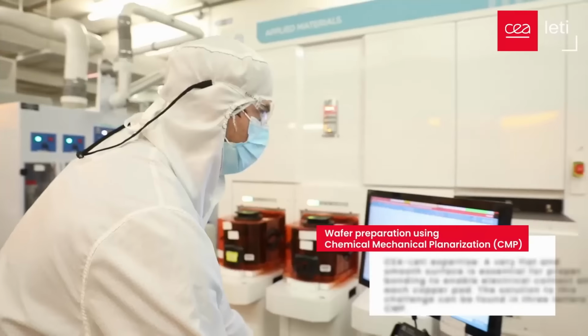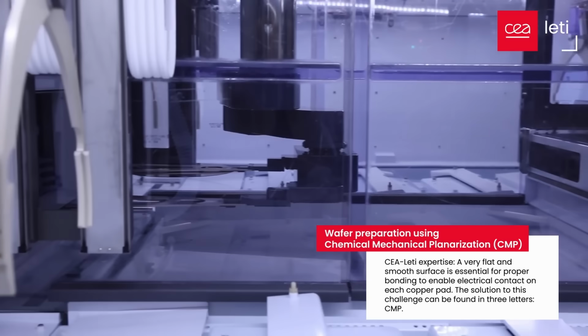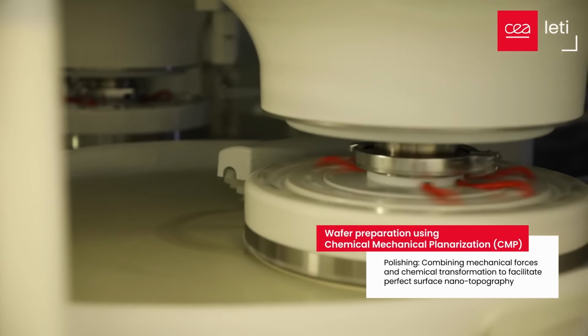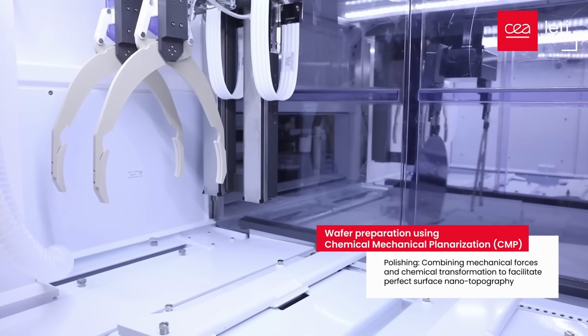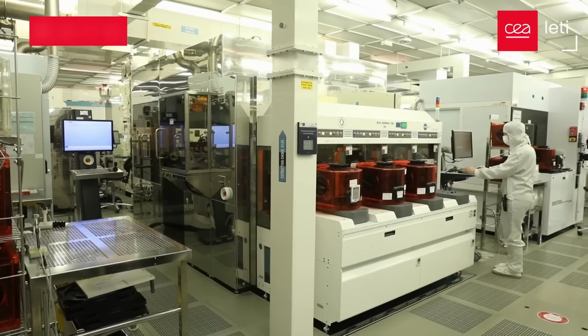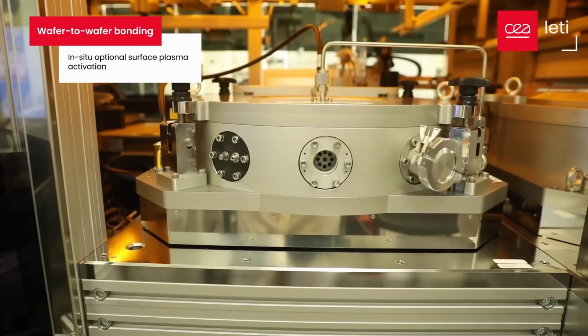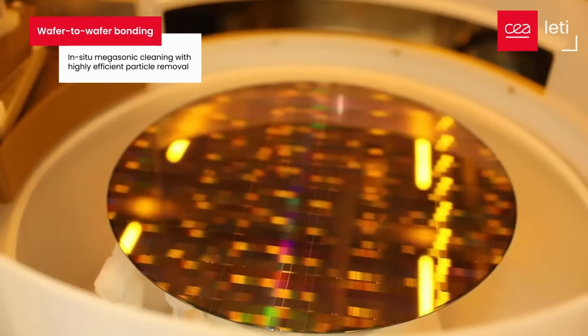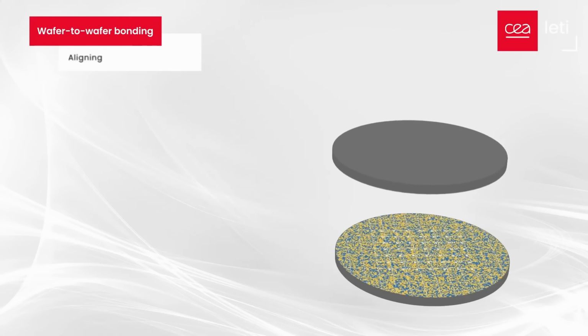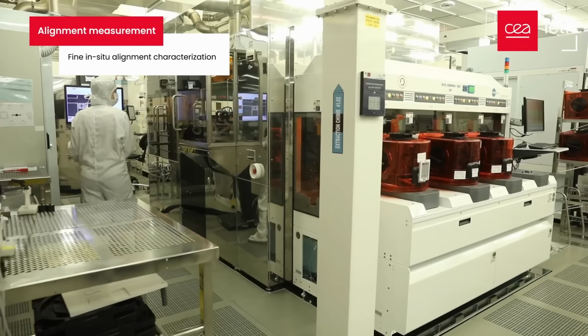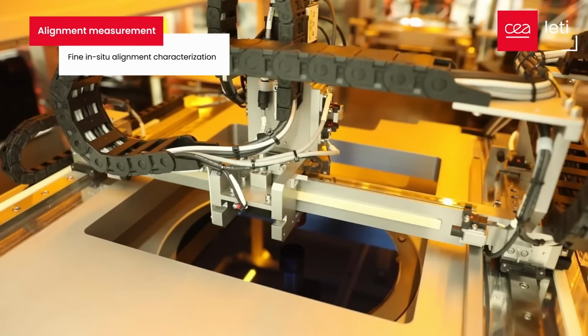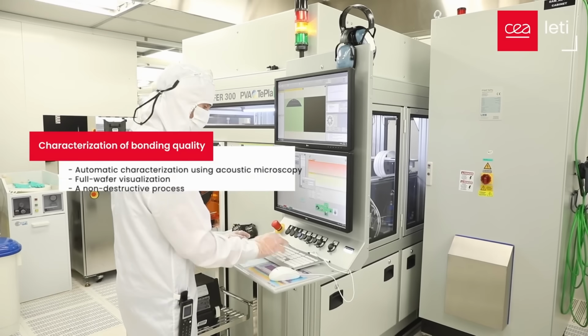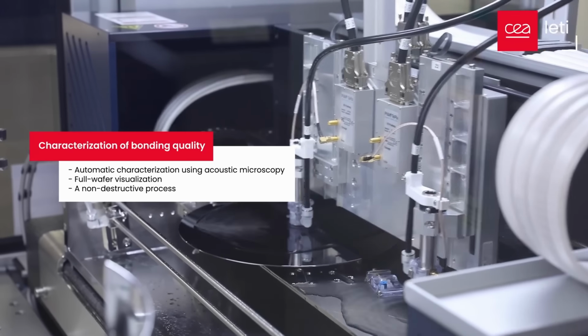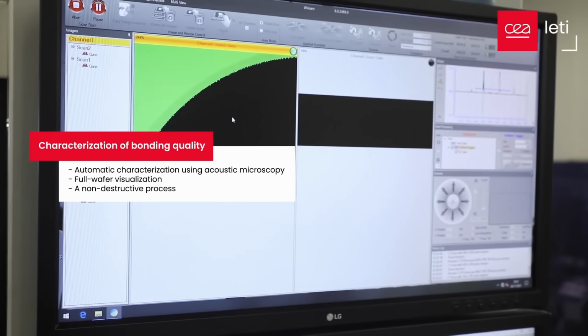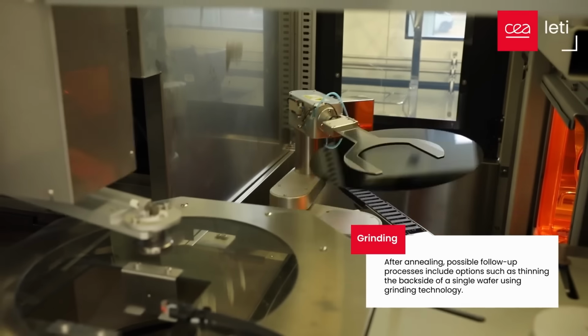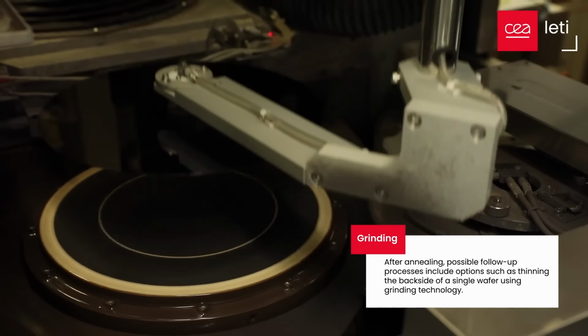Wafer-to-wafer, as the name implies, uses hybrid bonding to directly bond two whole wafers. The main advantage is that you have a high bonding throughput, as you bond entire wafers with little initial steps. For this type of bonding, the chips on both wafers need to be the same size, as they have to be perfectly aligned with each other. After both wafers are manufactured, they are prepared, which might require some wafer thinning. Next, the wafers are cleaned, the hybrid bonding layer is activated, and the wafers are bonded in the way we just discussed. Only after the bonding process is finished are the dies cut from the now double-stacked wafer.